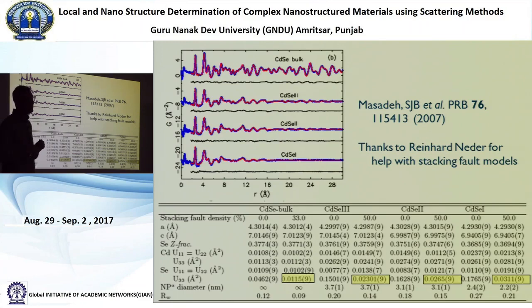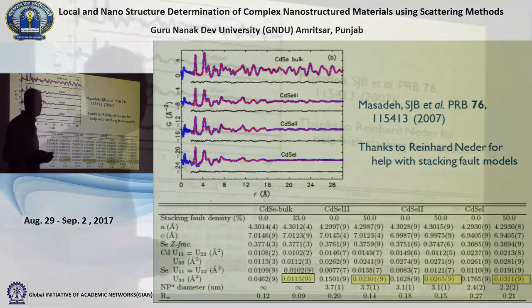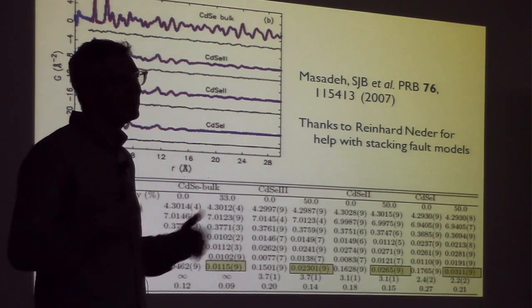So we're fitting a wrong model, and the model has some parameters in it that allow it to mitigate that problem. So it uses them. But then what people will tend to do is take this and try to interpret it as a physical thing, but it's just an incorrect model. So this is something that you always have to be careful about.